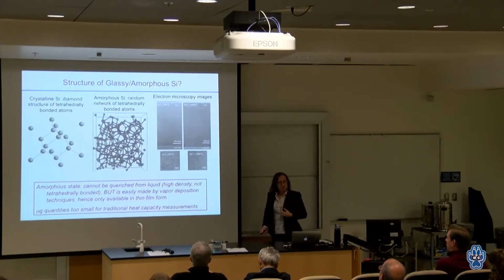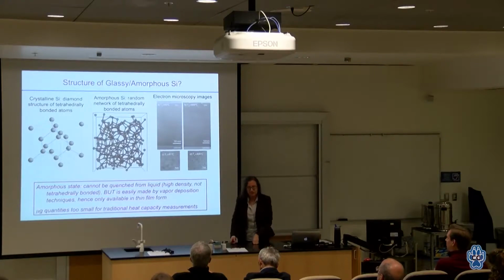But you can't quench silicon. And the reason you can't quench silicon is kind of interesting. The high temperature liquid state of silicon turns out to be fivefold coordinated. And that is entirely about entropy. And when I say entropy, it's the number of ways you can arrange things. So on average, every silicon atom in there is trying to be fourfold coordinated, but it gains so much free energy, entropy in other words, that it is better for it to have this sort of constantly changing set of bonds and who it's bonded to, and it ends up being effectively fivefold coordinated.